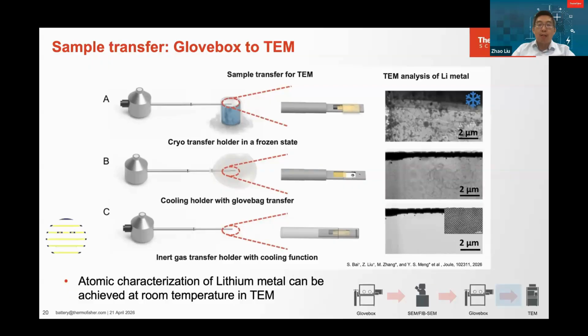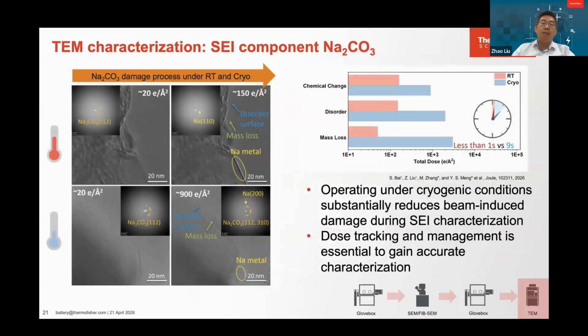One of the major reasons is the SEI component, which is more sensitive to beam damage. So in these cases, we used sodium carbonate, which is one of the key components of the SEI in a sodium battery, to do the analysis. The figure on the left shows a comparison between room temperature and cryogenic temperature and how the dose impacts the sample. As you can see, at room temperature, if the total dose goes over 150 electrons per angstrom squared, you already have severe damage on the sample.